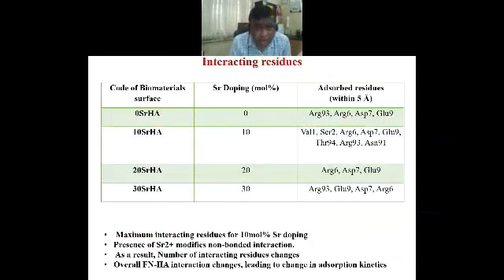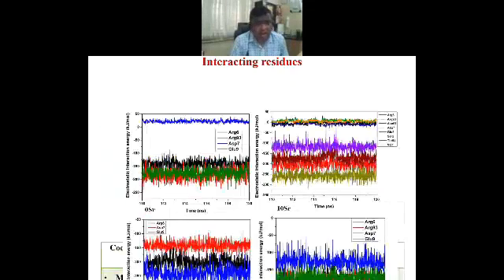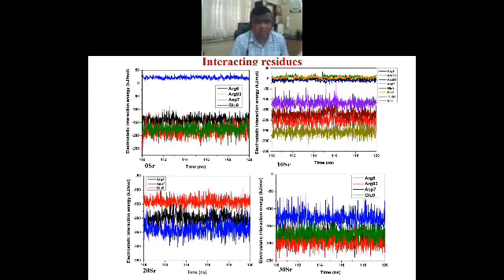Now, what are the different types of interacting residues? Here I must say, the more the number of residues, the better is the stability of the proteins which are getting absorbed. Here again, you can see 1, 2, 3, 4, 5, 6, 7, 8 residues are present when 10 mole percent strontium is doped to hydroxyapatite, compared to 3 or 4 residues in the other doped or undoped hydroxyapatite, which essentially reconfirms our earlier observations that it is the 10 mole percent strontium doped hydroxyapatite which will definitely enhance or favor better protein absorption on the biomaterial surfaces.